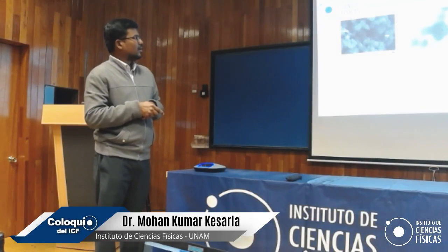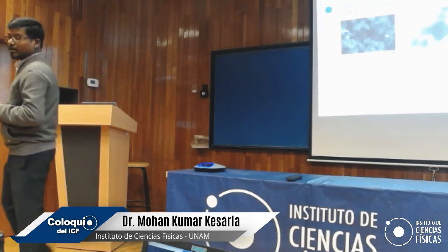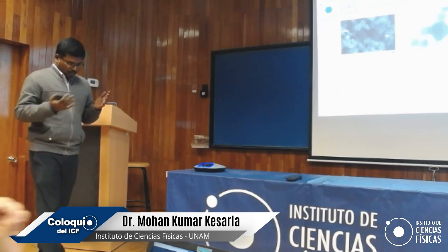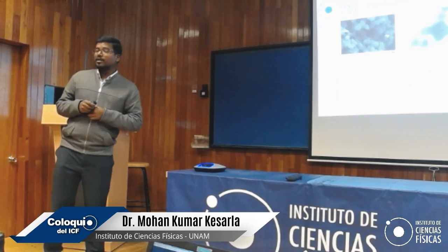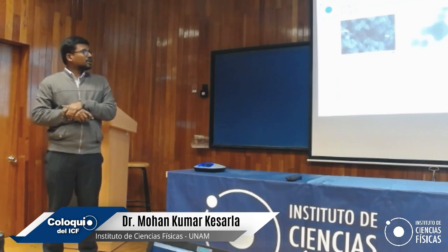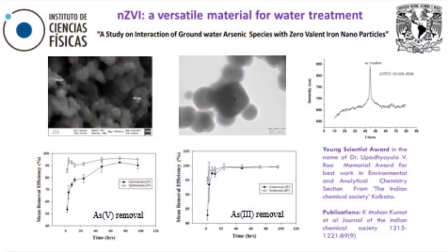And since this is a very thin layer of iron oxyhydroxide, you can't see it in XRD, so you can get only the peak of zero valent iron. So if you look at the arsenic removal capacities of this particular zero valent iron which we prepared, in almost 100 hours it is possible to remove 100% of the arsenic in the water, provided the arsenic is in plus 5 state. If it is in plus 3 state, it will take more time to get 100% removal.